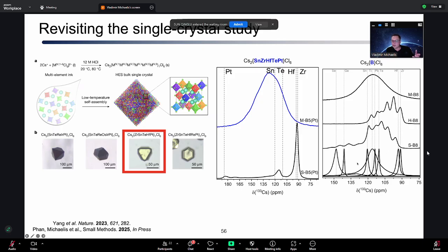Okay, this is an example here. This bottom one is all the parent samples overlaid. This is your 8-membered system using a solvent approach. This is an 8-membered system using a hydrothermal approach. And this is an 8-membered system using a mechanochemical approach. What you can see here is you get these domain formations in the hydrothermal or solvent approach, but you get what you'd expect in terms of a high entropy material if you use the mechanochemical.